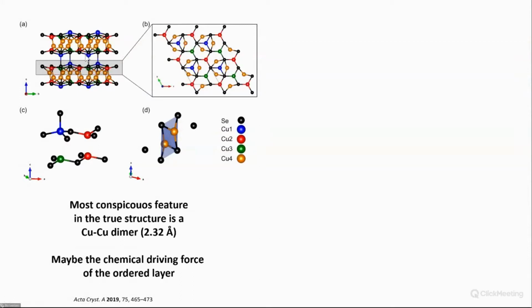And you can then say, have I learned anything at all? One of the things, because I think this is very important, is that diffuse scattering should not just be some mathematical discipline. We should actually try to learn about our structures. And one thing that's clear here is that in the true structure, you have a copper-copper dimer that you wouldn't see in the average structure distances. So this could be a chemical bonding feature that is really forming this local structure.